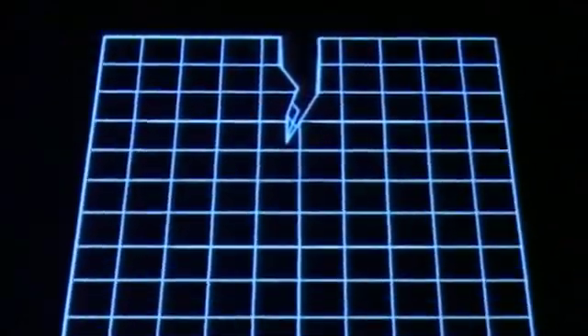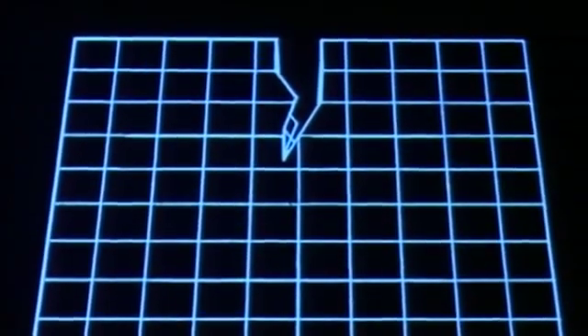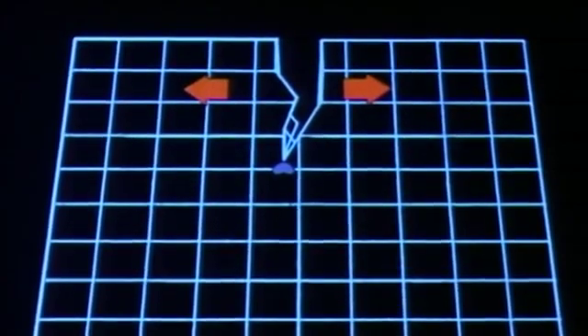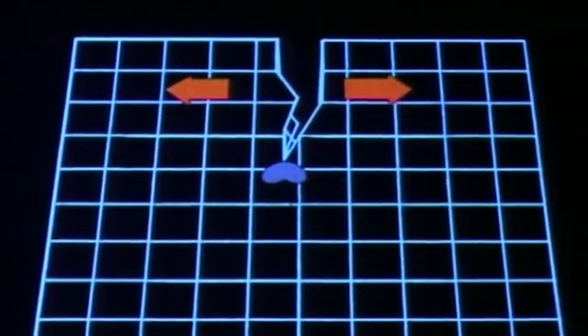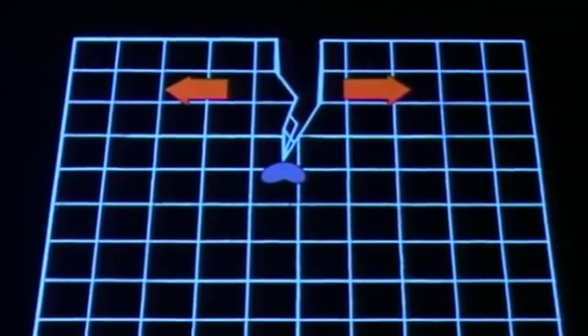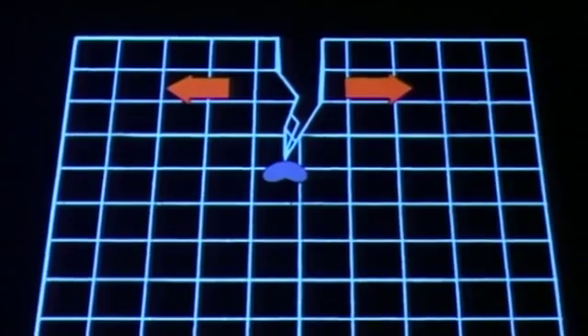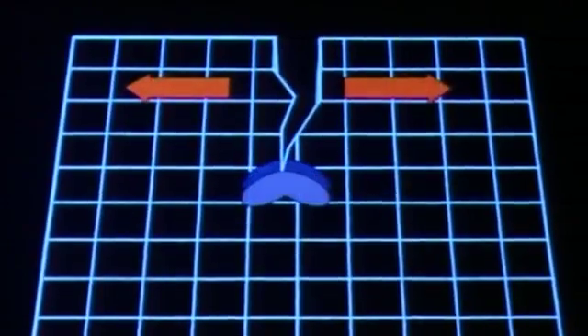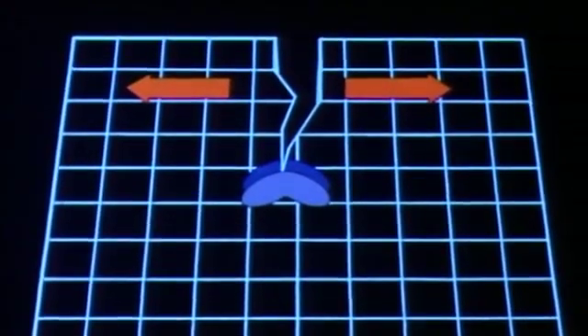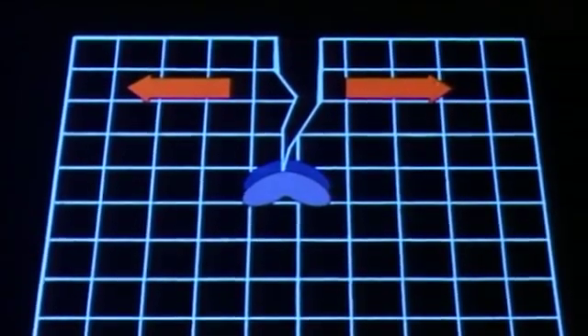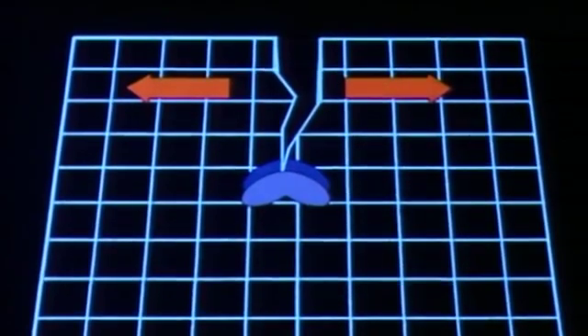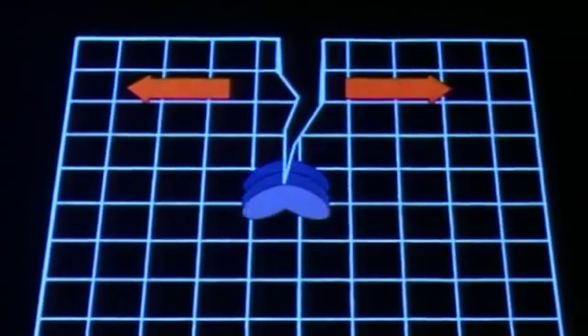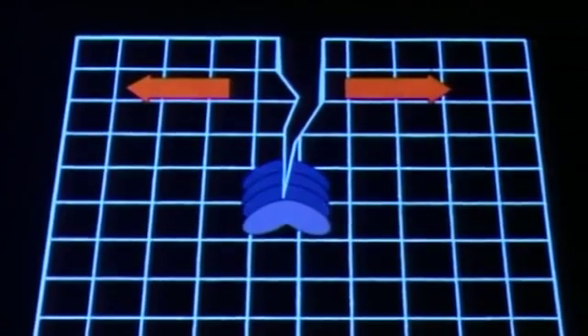If we start by applying a small load to the crack, then it will begin to open, and a small plastic zone forms at the tip of the crack. Increasing the load increases the size of the plastic zone. Eventually, the load will reach a critical value, and the crack will extend forward into the plastic zone. This happens when the stress intensity at the crack tip reaches a critical value, which is the plane strain fracture toughness of the material. As the crack tip moves, it's preceded by a plastic zone. Behind, it leaves a wake of previously deformed plastic material.